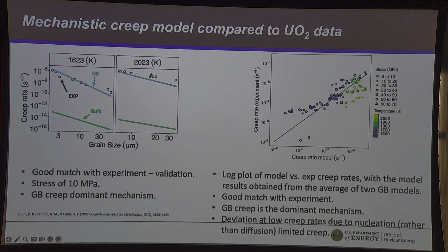This is just validation. What we get at the end actually does a remarkably good job describing the behavior of the materials as established in experiments. However, it's very clear that it is Coble creep, grain boundary creep, because this is the prediction for that mechanism. This is the prediction for the bulk mechanism, several orders of magnitude off. It's a very clear-cut conclusion, and a large set of data can be successfully described.